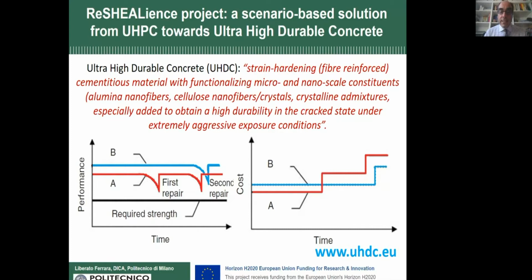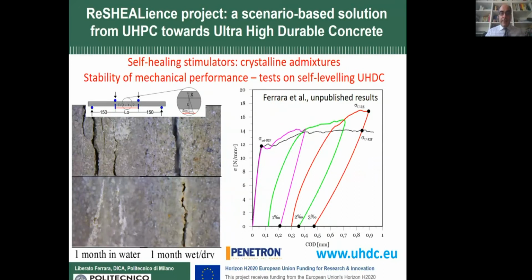So what did we do in order to go faster? We first of all investigated and assessed the possibility of stimulating the crystalline admixtures' self-healing performance. And you can see that not only do the cracks seal completely, but also the mechanical performance remains stable along repeated cracking and healing cycles. This performance is maintained over time.